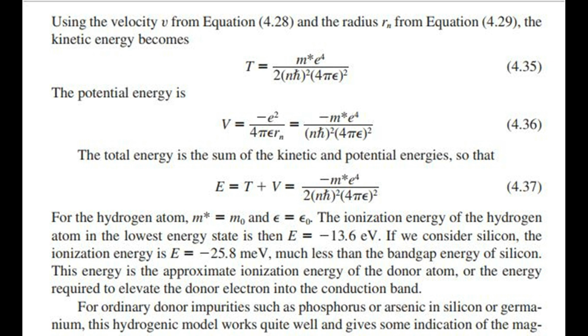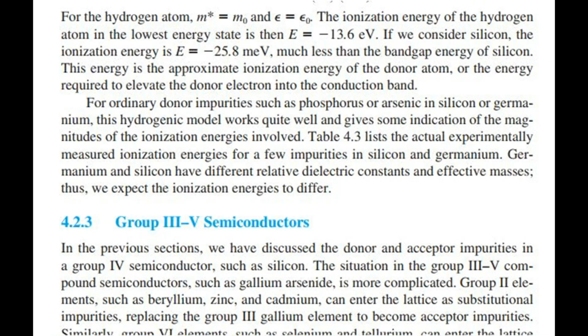If we consider silicon, the ionization energy is 25.8 meV, much less than the bandgap energy of silicon. This energy is the approximate ionization energy of the donor atom, or the energy required to elevate the donor electron into the conduction band. For ordinary donor impurities such as phosphorus or arsenic in silicon or germanium, this hydrogenic model works quite well and gives some indication of the magnitudes of the ionization energies involved. Table 4.3 lists the actual experimentally measured ionization energies for a few impurities in silicon and germanium. Germanium and silicon have different relative dielectric constants and effective masses. Thus, we expect the ionization energies to differ.